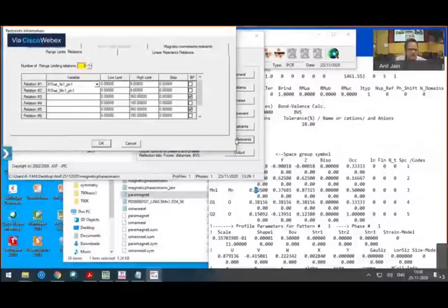We have to keep some constraints to get meaningful information from this simulated annealing file. What you can do is put some constraints. For example, you might have information from somewhere that the moments in these compounds are in the plane. So then accordingly you can put your theta and phi values and proceed.